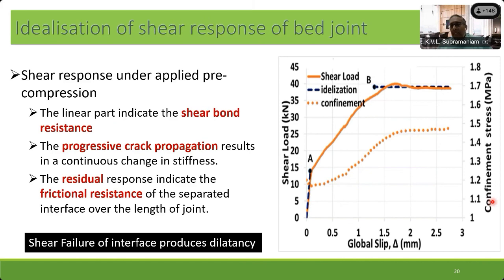Now, you may say, well, you're applying a constant confinement. Why would the confinement change? What we applied was an initial confinement. So I tighten the screws and apply a fixed level of compression on the triplet. Then I start doing my shear test. So the initial confinement is this value right here.